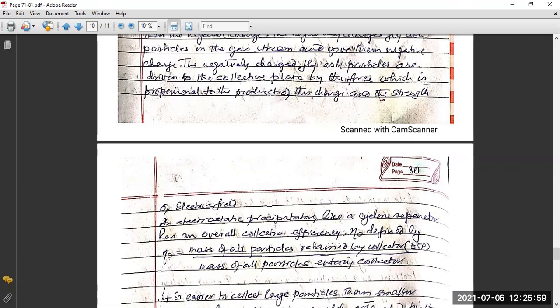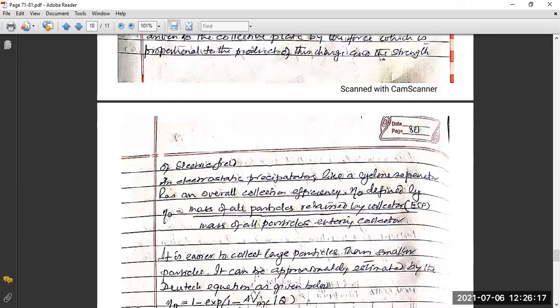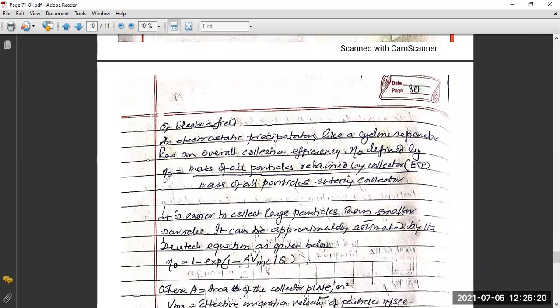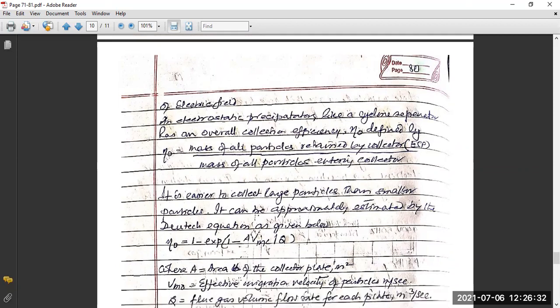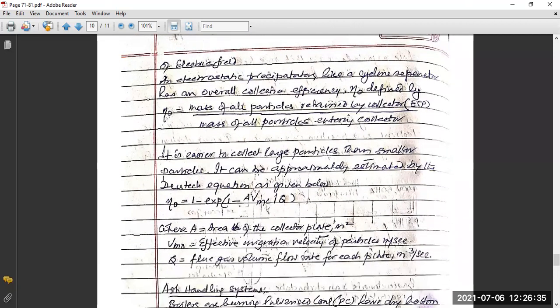An electrostatic precipitator, like a cyclone separator, has an overall collection efficiency, say eta 0, defined by the mass of all particles retained by the collector divided by the mass of all particles entering the collector itself. It is easier to collect large particles than small particles, and it can be approximately estimated by the Deutsch equation as given below. Eta 0 equals 1 minus exponential of minus A times w divided by Q, where A is the area of the collector plate, w is the effective migration velocity of the particle, and Q is the flue gas volume flow through each plate itself.